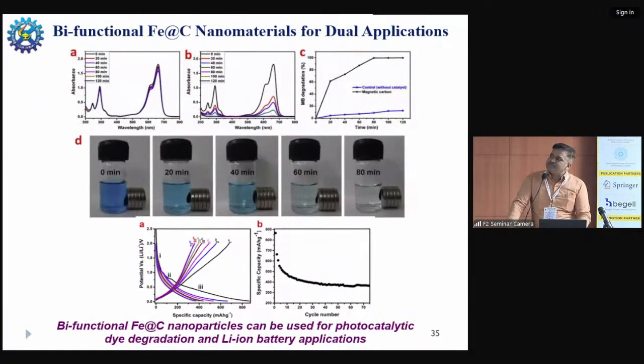And we tried to use this for two applications, one for environmental remediation, where we can see that the dyes are very nicely removed within a period of say 1 hour or so. And these materials can also be used for lithium ion battery applications as an anode, and that is what is shown here.